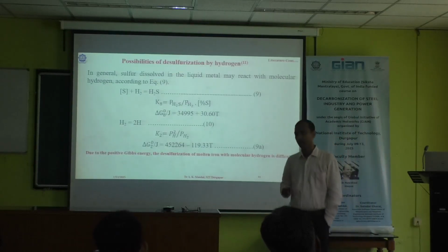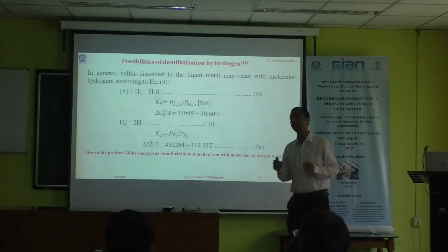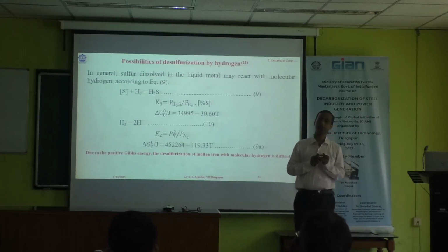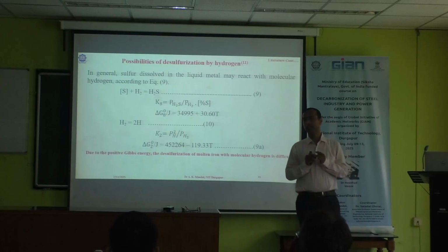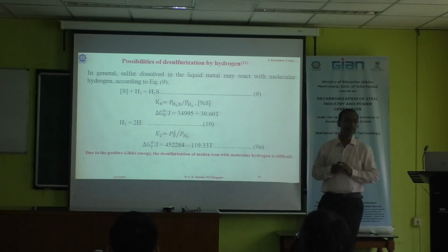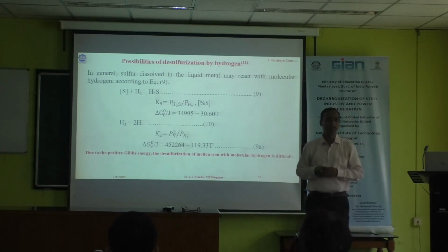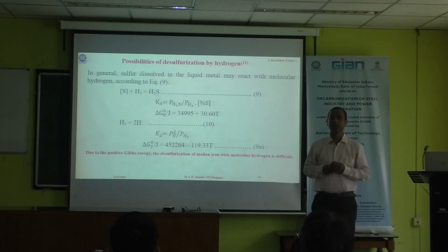Then what happens? If you see, the impurities are mainly carbon, silicon, phosphorus, sulfur. Carbon can easily react with oxygen, and it is already reacting. Therefore, it is removed through oxygen. All impurities reacting with the oxygen go to the slag. But the problem is for the sulfur.